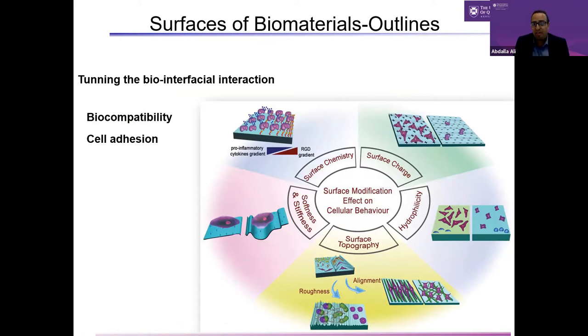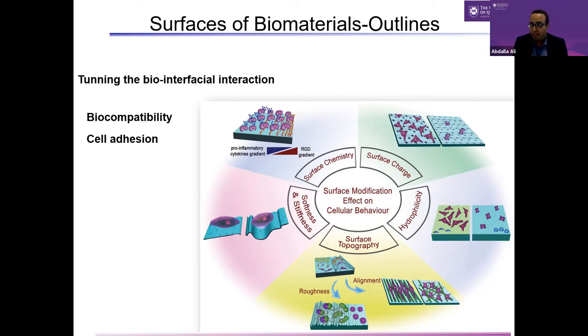Surface modification — the first interaction for biomaterials is detecting the surface of the implant or medical device. The immune system, once detecting the surface properties, will determine whether to keep the materials in the body or reject them. Surface modification plays a very important role for success at the early stage of implantations. Different functions can be improved through the surface, like surface charge, surface energy, hydrophilicity — we can tune hydrophilicity or hydrophobicity depending on the target application — surface topography ranging from nano to micro, and texture characteristics such as nanotube, plate structures, rods, and so on. These always change the sensing of the cells, like mechanotransduction as well.